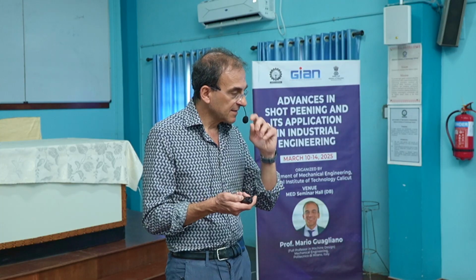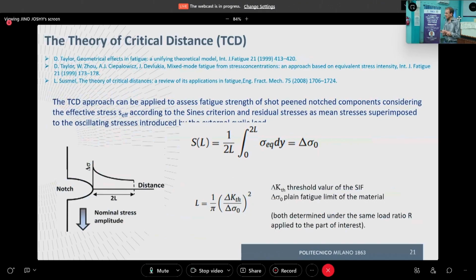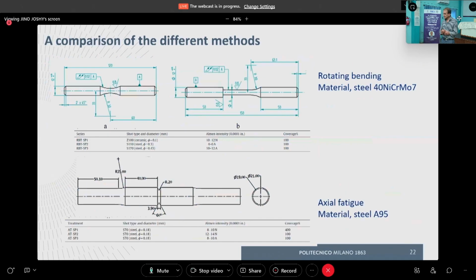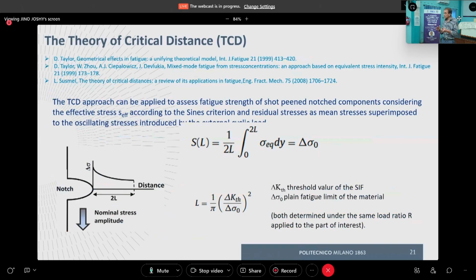And how can we consider shot peening with this criterion? We can consider shot peening in terms of residual stresses, by considering the trend of the equivalent stress not only in terms of applied stresses, but also in terms of effective stress, that is the sum of the applied and the residual stresses. And from a conceptual point of view, that's all. I don't want to go deeper, just to let you know that there is this criterion that can be used.